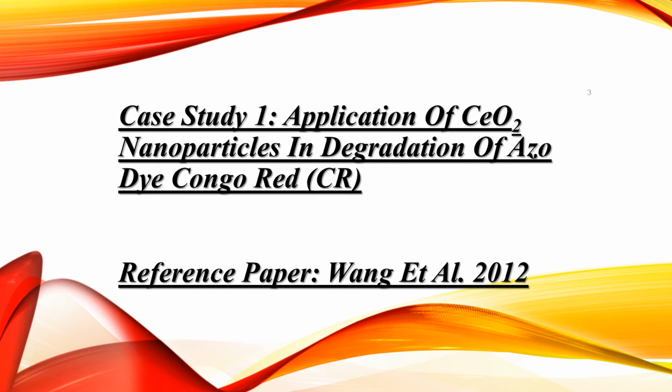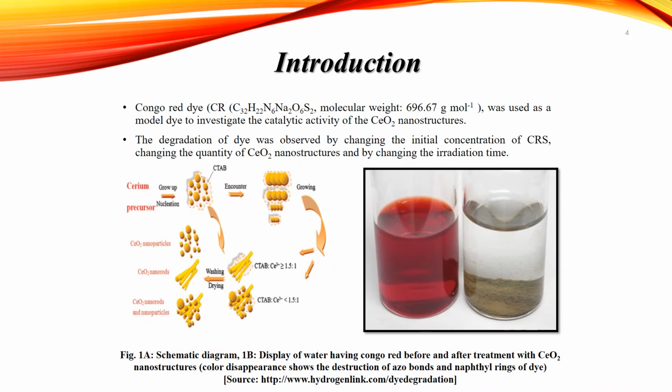I'm here to present the application of CeO2 nanoparticles for degradation of azo dye Congo red. Coming to the introduction, Congo red dye is being used as a model dye to investigate the catalytic activity of the CeO2 nanostructures. The synthesized particles are shown in figure 1A: nanoparticles, nanorods, and a mixture of nanoparticles and nanorods. Figure 1B shows water having Congo red before and after the treatment with CeO2 nanostructures. Color disappearance is mainly due to the destruction of the azo bonds and naphthalene rings of the dye.